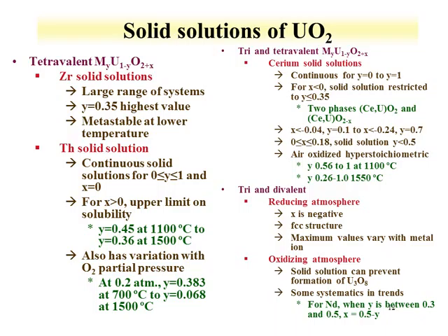Unlike zirconium, thorium has an ionic radius very similar to uranium. They're both about 1 angstrom, whereas zirconium is about 0.72 angstrom, so it's much smaller. Thorium makes a solid solution with uranium over the entire range.